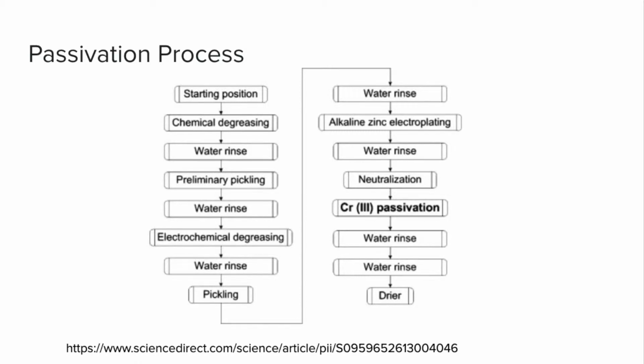First of all, to overview this process, the material is first chemically degreased. Pickling can remove up to 40 microns from the surface of the material. This is important because it can remove some surface defects and also inclusions that are found in the material that could resist the passivation process. It is important that the surface of the material be completely free of any defects and inclusions so that the passive layer can be complete. Passivation is then performed by dipping in an acid solution of either citric or nitric or other acids as well.